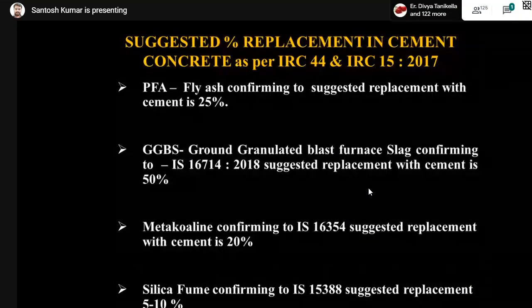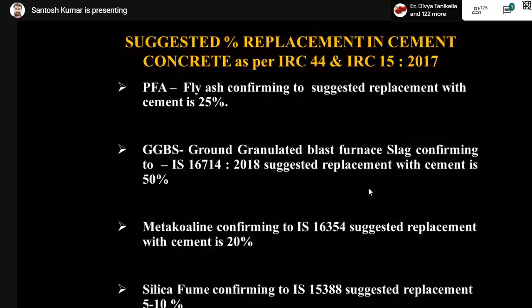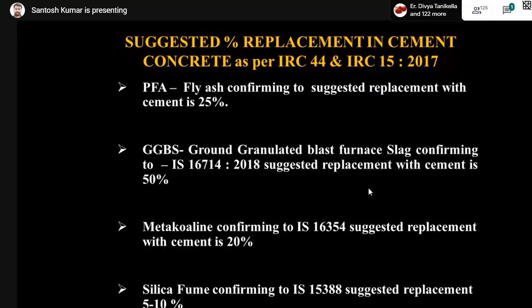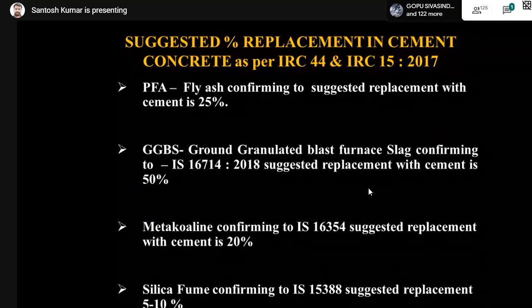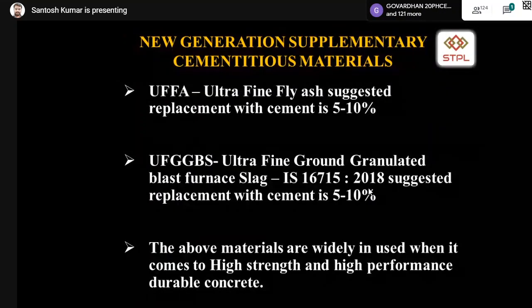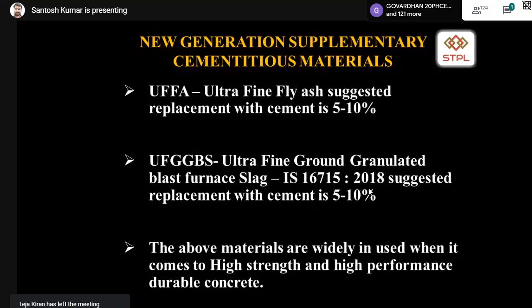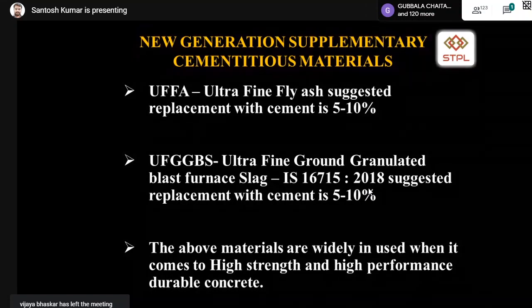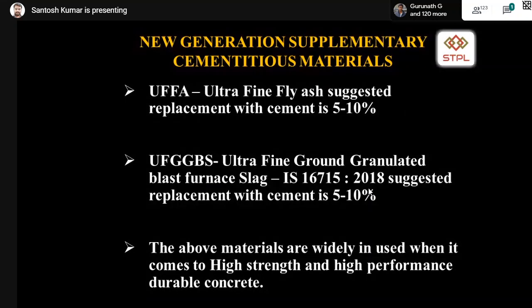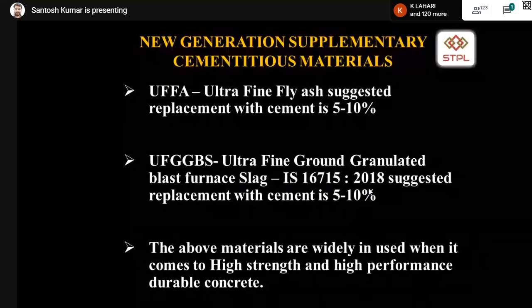And suggested replacement in cement concrete as per IRC 44: fly ash can be used up to 25%, GGBS 50%, metakaolin 20%, silica fume 5 to 10%. And there are new generation supplementary cementitious materials which are in the market. Ultrafine fly ash can be used up to 5 to 10%. A standard is not yet published, it is in the draft mode, and I think by December 2020 there will be an Indian standard on ultrafine fly ash. And ultrafine GGBS, which is nothing but Alccofine, we can use up to 5 to 10%.